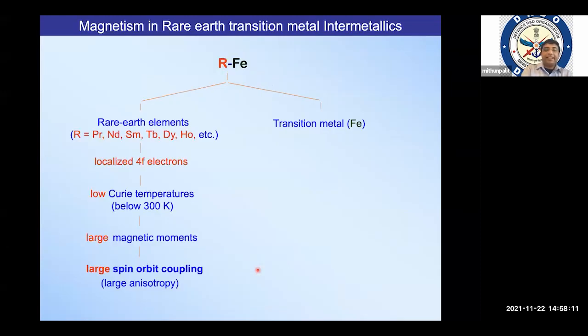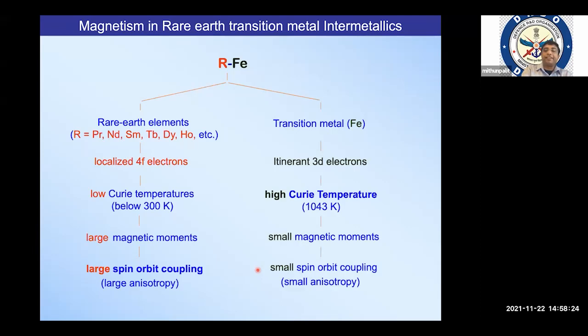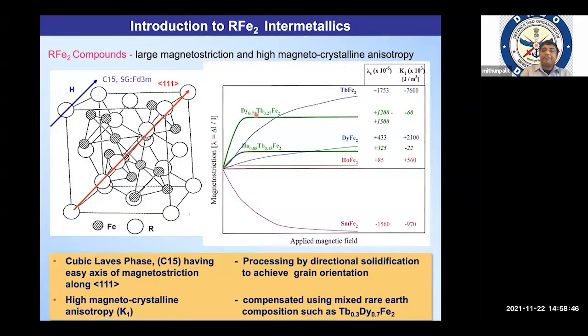So you can see that the rare earth materials, due to the source of magnetization from the 4f electron and spin orbit coupling, have Curie temperatures much below room temperature, whereas transition metals have high Curie temperature, but they have very low spin orbit coupling. This spin orbit coupling is the factor which controls the magnetostriction in a material. As usual, the rare earths having a large spin orbit coupling have high magnetostriction compared to transition metals. So therefore, combining them, if we take a ternary Dy Tb iron, such material has very good magnetostriction with Curie temperature above room temperature.